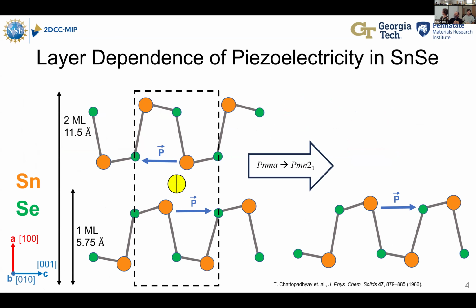Tin selenide is a layered material, so it has van der Waals bonding, and its unit cell consists of what I call two individual layers. The polarization direction in each individual layer is in the reverse direction. So because of this central symmetry in bulk, multilayer tin selenide should not have any piezoelectric effect. But if you reduce this to one layer, which would be half of a unit cell, that gives you your predominant polar direction. So this is one of the reasons why we need layer control in tin selenide. If we want to access this piezoelectric effect, we need to have this single layer of tin selenide.